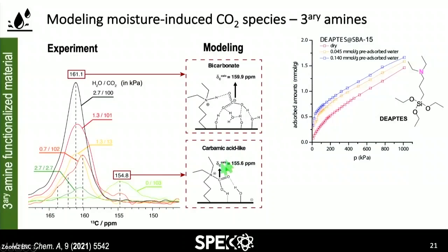And here in this case, if you look at the NMR, it's again quantitative NMR data. If there is no water in the system, so if you just absorb CO2, you see that there is a very weak peak. Well, not so weak, but there's a weak peak. You see that there's a lot of noise at around 155, which can be maybe attributed to a carbamic acid-like species. The calculated chemical shift fits very well with our experimental data. And as long as you start putting a little bit of water, you start seeing the 161 peak coming up, which increases when you increase the water content, and that one is attributed to bicarbonate.